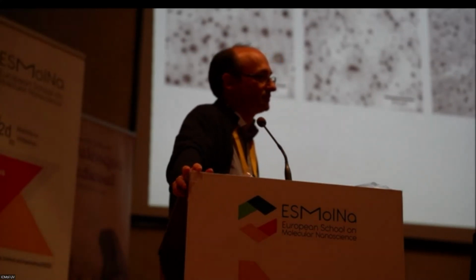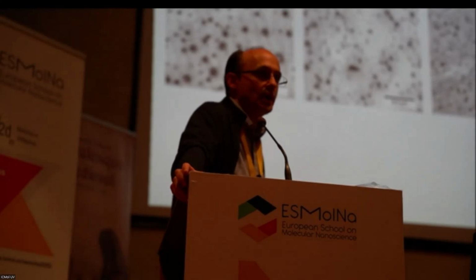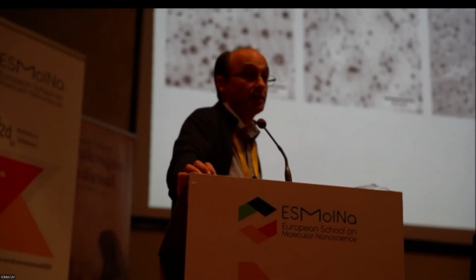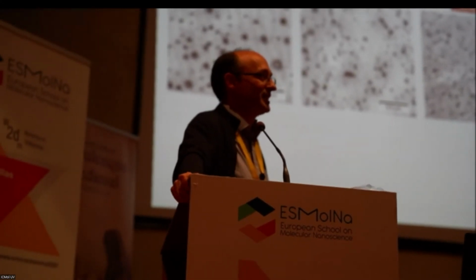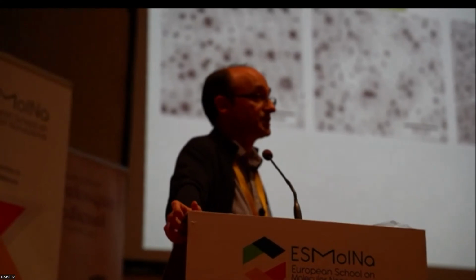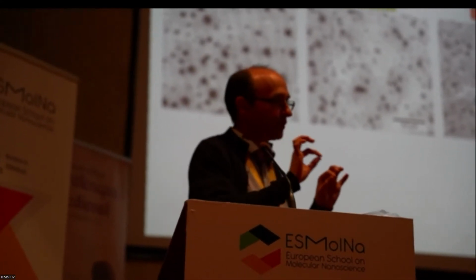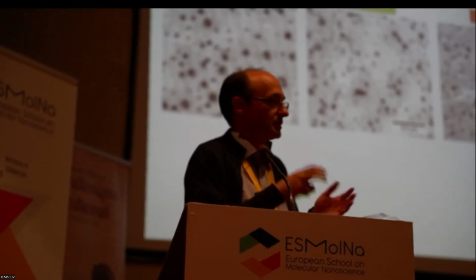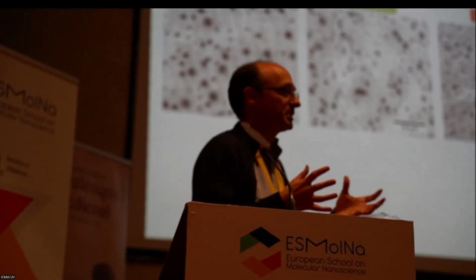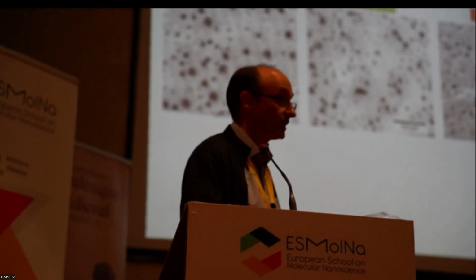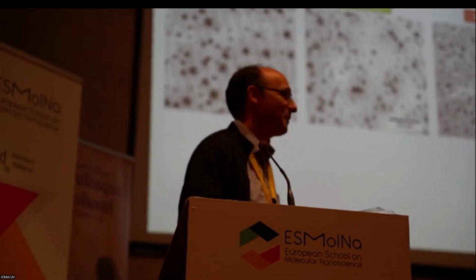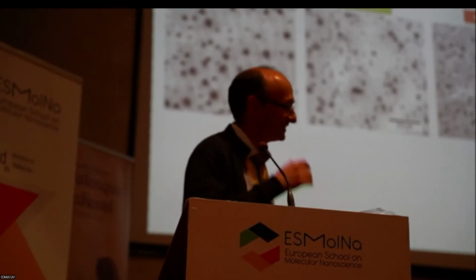But how about trying with polymers that are more functional in themselves? We have been trying, for instance, with conductive polymers, in collaboration with Mariluz, and sometimes the difficulty is finding the right way to form that material. So this is very easy. When we move to other polymers, sometimes it's much more difficult. But it's something really interesting. For instance, for sensors, this is quite interesting. You have very high surface area. You are able to locate on the surface of the cell walls your material with sensor properties. You can have very nice selectivity, etc. It's something that we would like to do, but it's still all in our minds.